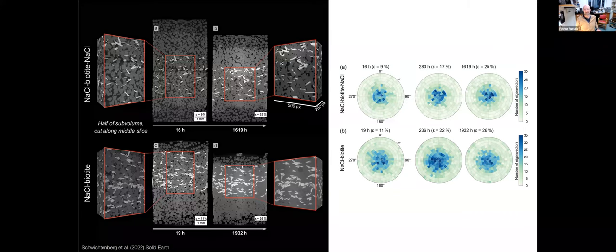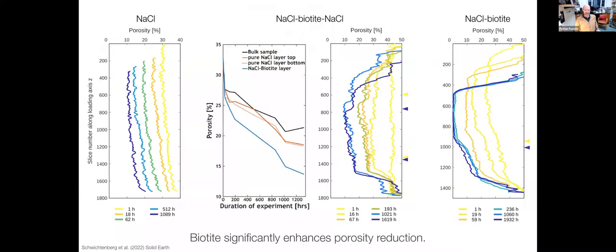So, quite interesting insights. The other thing that we did observe was that the porosity, and I hinted at that earlier, decreased quite significantly in the biotite bearing layers. So what we see here is the control sample, where the porosity decreased uniformly as a function of compaction. That's no surprise. Here we have the sample which has halite, biotite, halite. That's the entire bulk sample, porosity reduction, top layer, bottom layer. And you can quite clearly see here the porosity in the central biotite bearing layer is decreasing more.